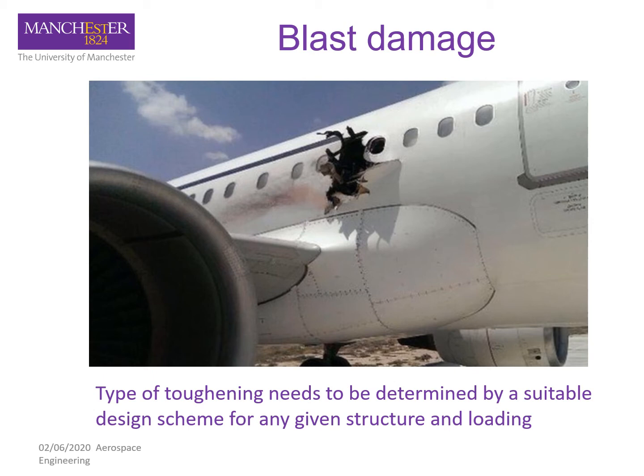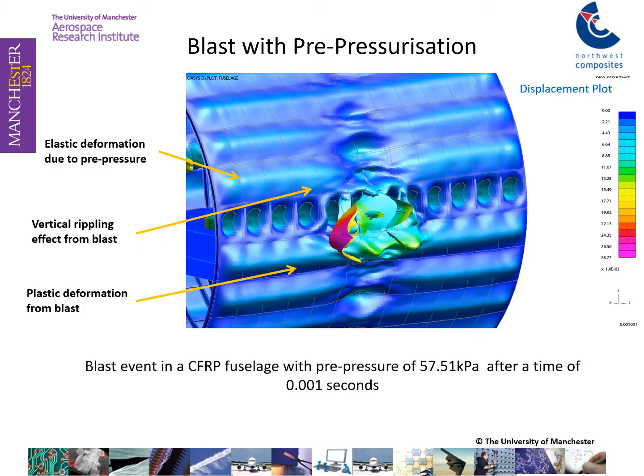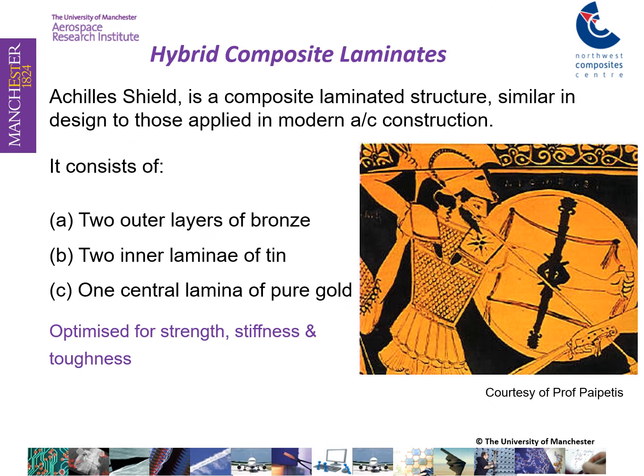structure and loading. Here is a metallic airframe, and you can see that it cannot prevent perforation. Even a carbon fiber cabin is not going to be able to prevent that perforation from taking place. So we need a different solution, since the monolithic metallic or monolithic carbon fiber, both systems are unable to contain that blast energy. However, the combination of metal and composite might be able to contain that blast energy.